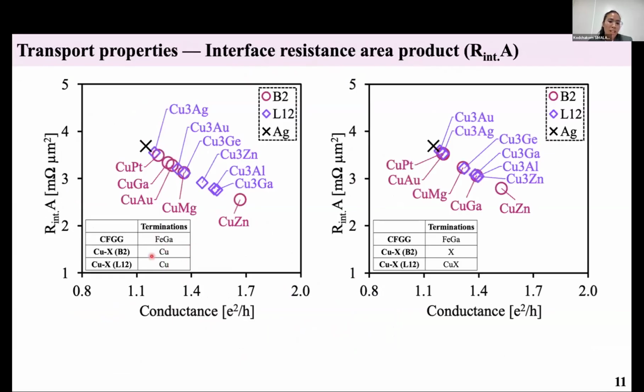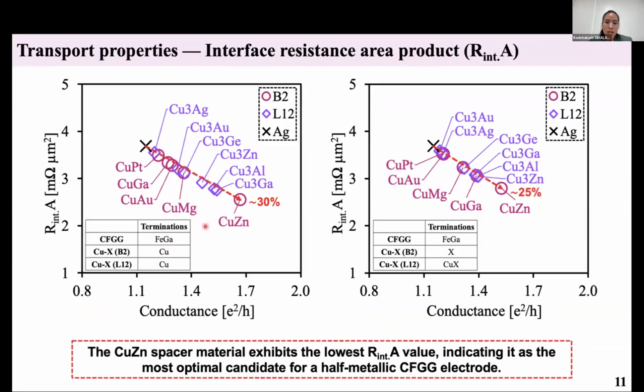I show it with the different terminations as shown here. So you can see that the copper zinc spacer material provides the lowest RA value, indicating it is the most optimal candidate for the half-metallic CPP-GMR electrodes. Specifically, it provides approximately 30% RA reduction compared to the Ag spacer for the copper termination and around 25% RA reduction for zinc termination. Then the analysis of the Fermi surface matching, comparing between using the Ag spacer and copper zinc with the copper termination, which is the more stable interface, will be presented on the next slide.